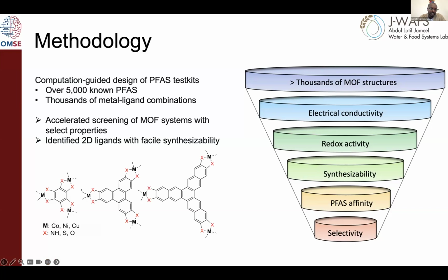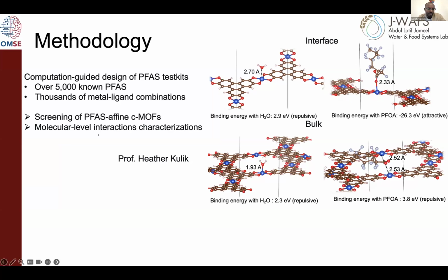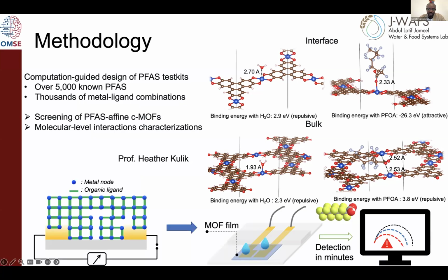But these are the building blocks that we settled on, where these are conjugated ligands that we use to make these frameworks, and we're using coordination with metals such as nickel and copper. You essentially make a 2D porous polymer, which does not leach into water. And we're interested in how they interact with PFAS. Here we collaborated with Professor Kulik at MIT on evaluating the interaction level with these materials. For example, if you have a metal site in these coordination polymers, could we identify and optimize how these materials interact with different PFAS? So we started with a computational viewpoint, and as I mentioned, we settled on a few candidates here. And again, once we identify which ones have the strongest affinity, we're interested in these resistive devices where we're measuring the change in the current when these materials bind with the PFAS.